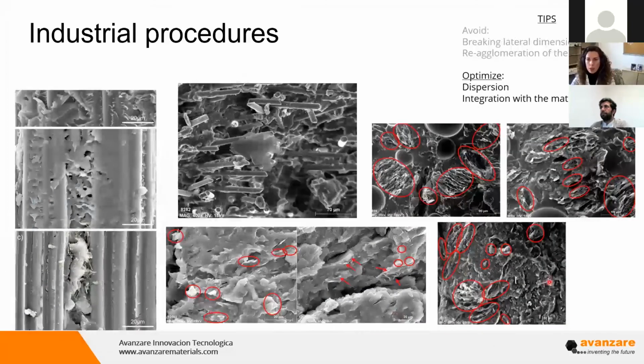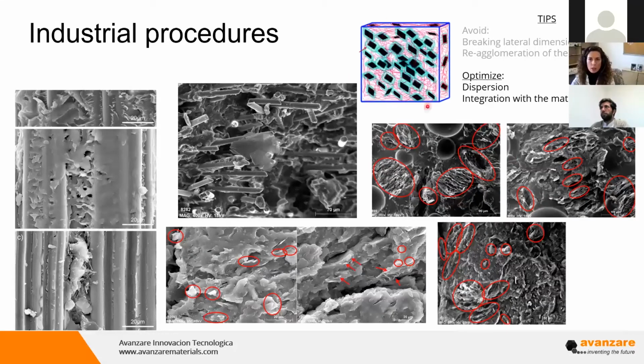Also, it's necessary to avoid the reagglomeration. For example, in these same micrographs, we can observe that in all the matrix, we have some parts filled with graphene reagglomerated, but others are empty. So if we take in mind that to have a homogeneous material we have to achieve this, surely this would not be a good idea. Another aspect to take into account is to have a good interface with the matrix, because the better the interface, the lower the resistance due to this interface. Okay, so the dispersion and integration with the matrix is really important to take into account.